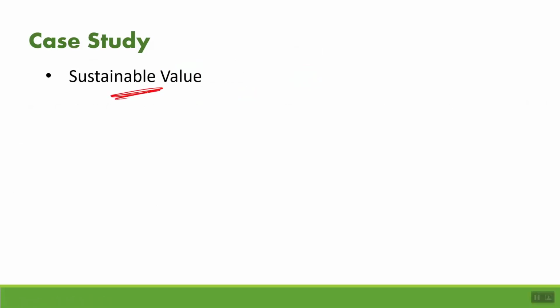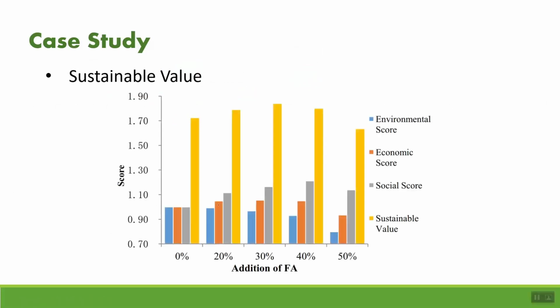Then a sustainable value is calculated for each case. As can be seen, for a replacement percentage of 0% indicating an ordinary reinforced concrete, it has a sustainable value of about 1.7. Then the sustainable value increases for the replacement percentage of 20%. Then it reaches the maximum sustainable value for a percentage of 30%. Then it reduces again for about 40%. Then the least amount at a replacement percentage of about 50%. As can be seen from this figure, the optimal fly ash replacement ratio is about 30%, indicating the highest sustainable value.